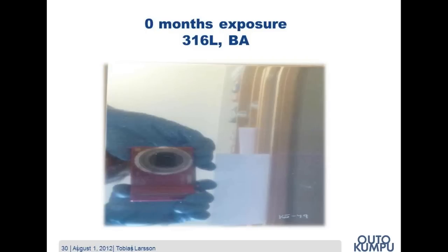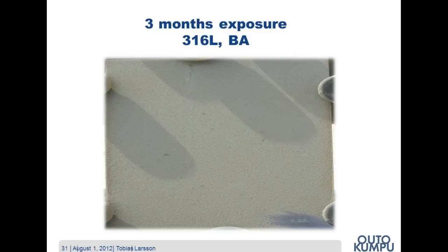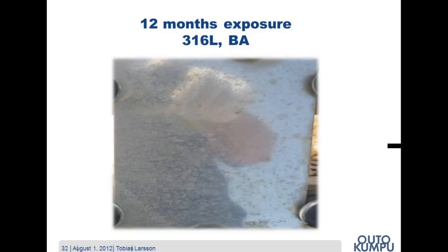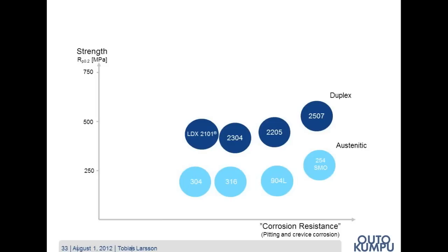Here we have the same grade but with a bright annealed surface finish, which is almost like a mirror, because the smoother the surface finish, the better the corrosion resistance. It is a bit difficult to see from the 3 months results since we did not brush off the dust, but it has a visible light corrosion. However, we can clearly see from the 12 months results that the 316 is not good enough, not even with the bright annealed surface finish.